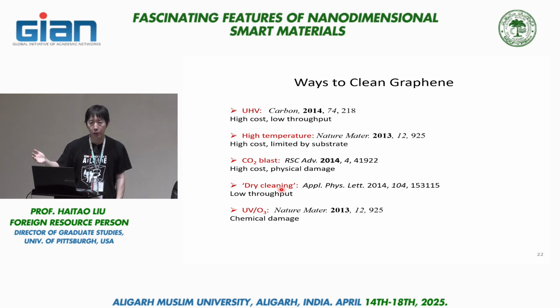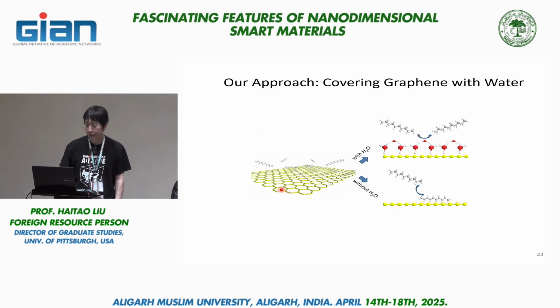And of course, there are chemical ways you can oxidize the surface. And as they showed, in the case of TiO2 and in the case of ceramic material, you can simply apply a high temperature, and that would drive off the hydrocarbon pretty easily. We showed that, as I mentioned earlier, simply by covering the surface with water, we can prevent the hydrocarbon absorption. And the evidence seems to suggest that you can form a monolayer amount of water on the graphite surface. And this is quite surprising to us.